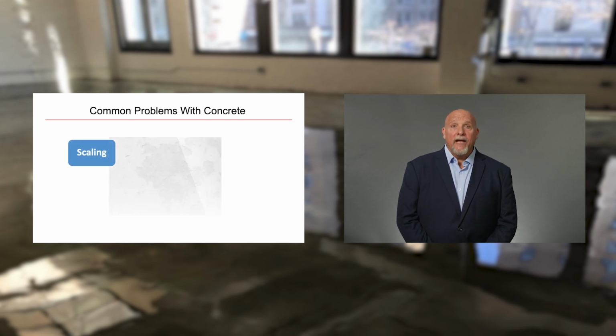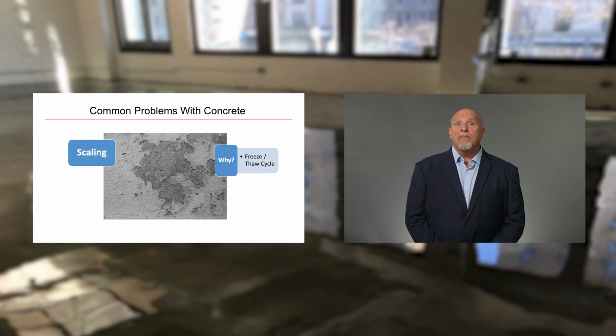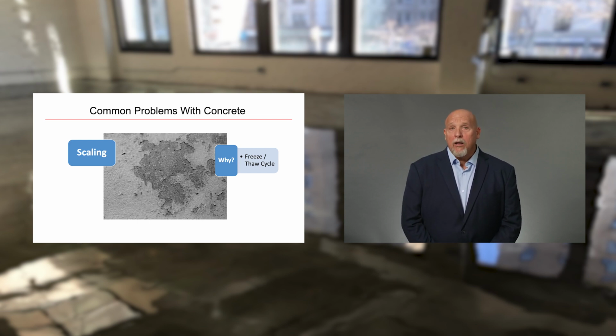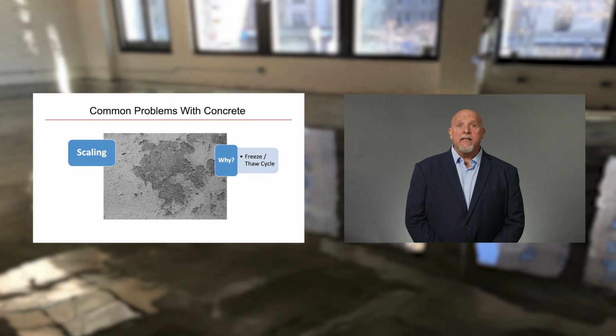Scaling is local flaking or peeling of a finished surface of hardened concrete as a result of exposure to cycles of freezing and thawing. When the hydraulic pressure of the expanding ice exceeds the tensile strength of the concrete, scales of mortar detach from the surface, exposing aggregate. Generally, it starts as localized small patches which later merge and extend to expose large areas.